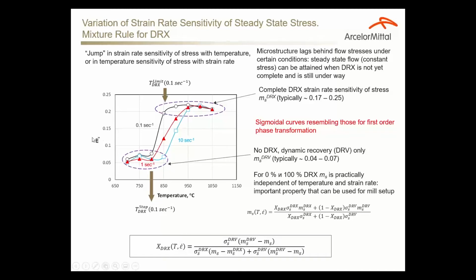So when we determine the strain rate sensitivity from our Gleeble test, we can easily translate it into mill data, saying, look, guys, you have to enter this value or this value into your model, and then you will be okay in terms of avoiding recrystallization or facilitating it. For curiosity purposes, we can calculate the volume fraction of partial recrystallization using the conventional lever rule or mixture rule for sensitivity.